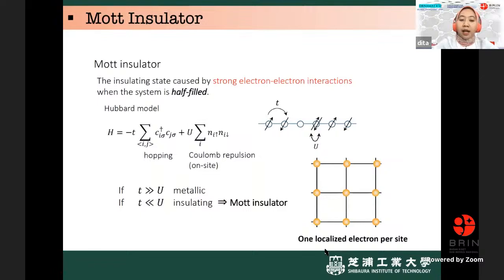Okay, then I introduce the concept of the Mott insulator: if we have one electron per site in the lattice of a material like this, in this case, we expect the material to have metallicity, but when we measure the resistivity, it becomes an insulator. So what's happening here is the so-called Mott insulator.